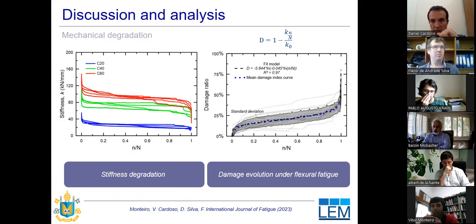So this makes sense because the more fibers in the cracked section, we have a higher flexural residual strength, which promotes higher stiffness of the cracked material. With the stiffness decay, we can also propose some empirical equations to verify the damage in terms of stiffness along the fatigue life.